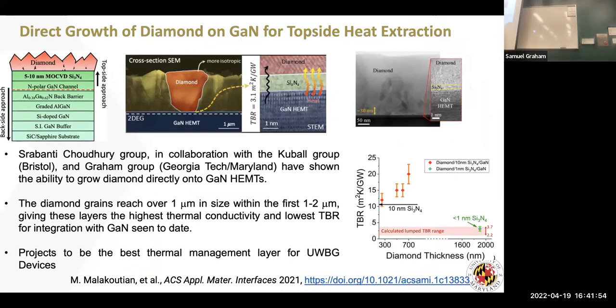Again, I talked about putting this transducer layer on top to spread the heat. This is working with Srabanti Chowdhury from Stanford, growing diamond on top of gallium nitride HEMTs and on top of AlGaN that we're doing right now. She's developed a method to really expand the width of these diamond crystals. And so when we've looked at some of our previous diamond work and what we've been doing with her, this actually has extremely high thermal conductivity for even films that are about 1 micron. So we can get these thermal conductivities up to 500 watts per meter K. So remember I said before, you don't have to go to 1,000. So this is getting us a good dielectric material around 500 watts per meter K.